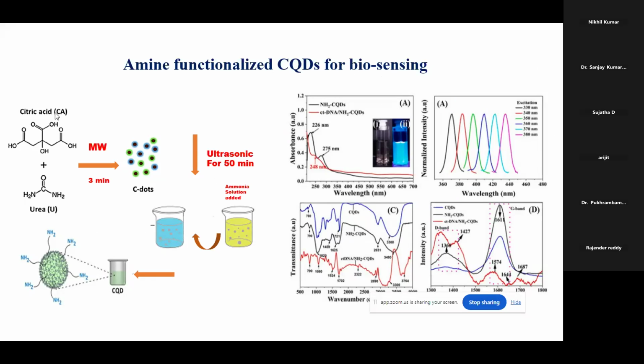And microwave for 3 minutes, we can obtain NH2 functionalized carbon quantum dots by using the ultrasonication method. I also added ammonia solution into it, so I can get NH2 functionalized into the system. So it's a functionalization. With this one, UV shows 226 and 275, which give the CN bond formation, and it shows excitation-dependent emission. This one is collective with the DNA because it has a negative zeta potential of about minus 25. So we just add this NH2 with that calf thymus DNA.